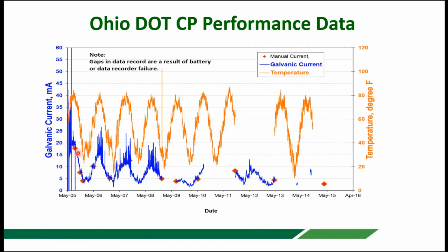continuing along. And the blue line is measuring the current that's going from the anodes to the steel, and that is high in the summertime and lower in the winter, higher in the summer, and continues along. But you'll see that it doesn't go to zero even in the middle of winter. Even though the temperature is getting below freezing in the middle of winter, it's still actually passing current to the